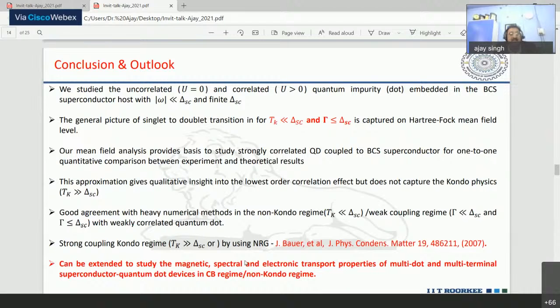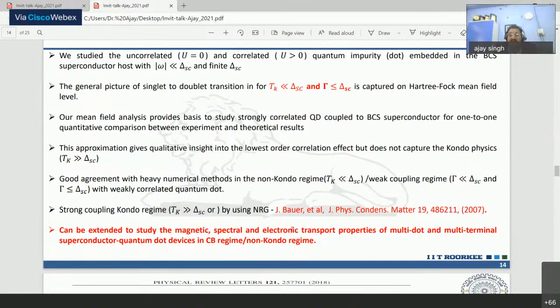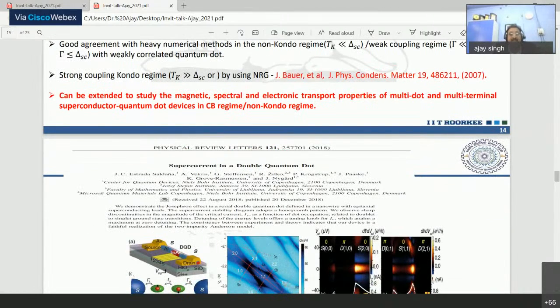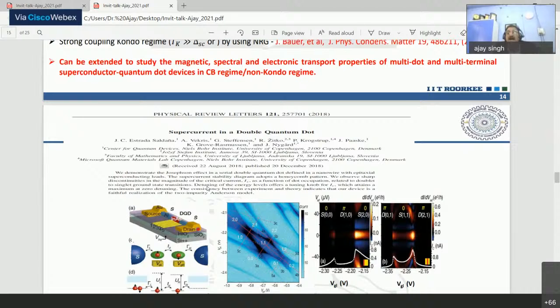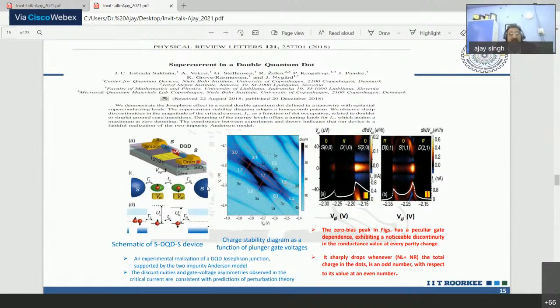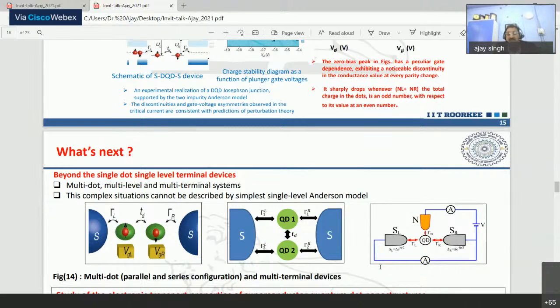So with this, we have tried to extend this result to the strong coupling regime and extended the other properties using multiple 2-dot and 3-dot terminals. And there is a very recent experiment where the double dot supercurrent was measured by this Denmark group. And these results are very interesting because these double quantum dots embedded in superconducting leads are an experimental realization of the two impurity Anderson model in superconducting leads. And here the discontinuity in the conductance is seen at a certain point. And this discontinuity leads to a 0-pi phase transition. And you can see the doublet here. But whenever there is a transition from singlet to doublet, there is a discontinuity in the conductance. So these results are very interesting, and they are beyond mean field calculations.